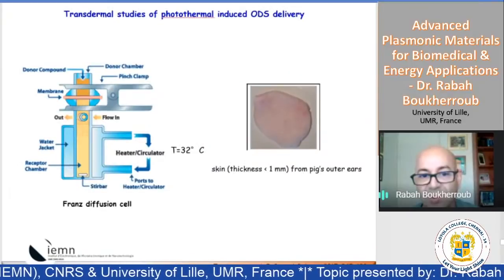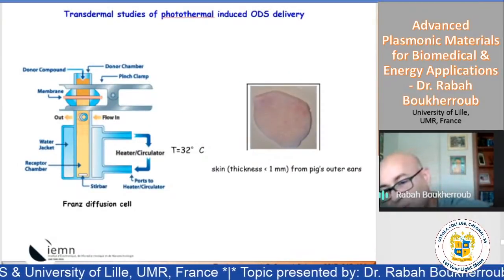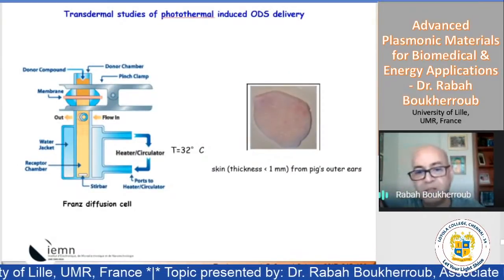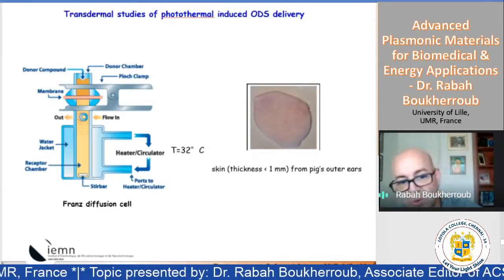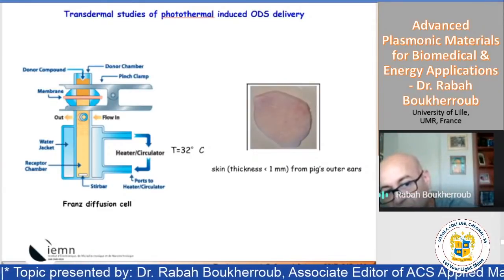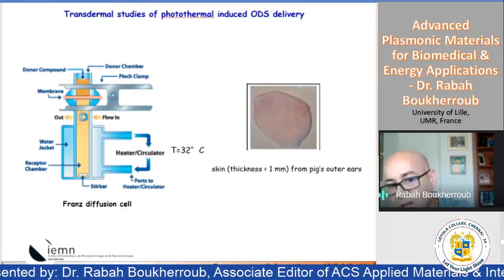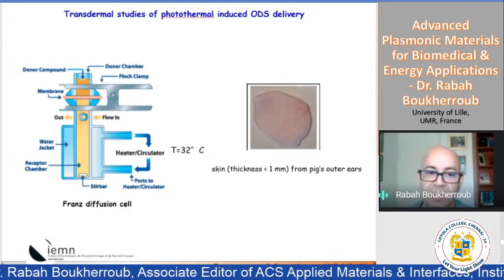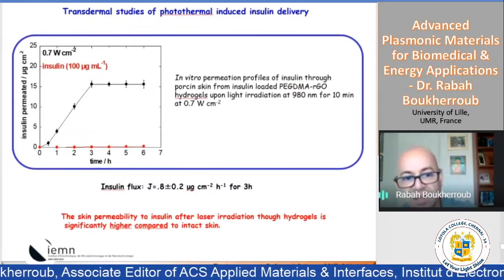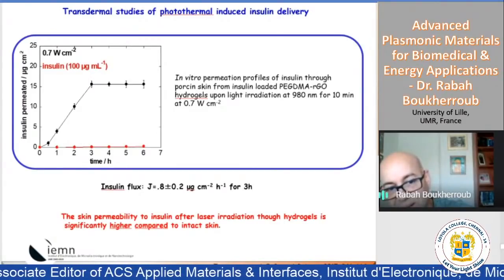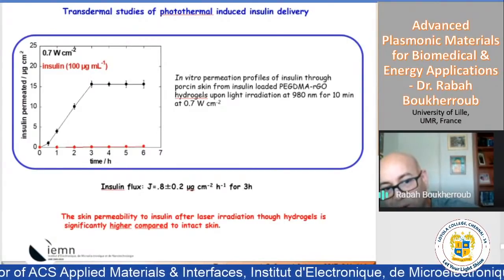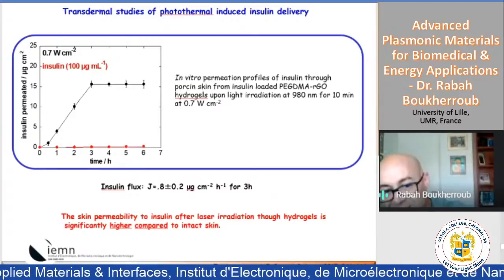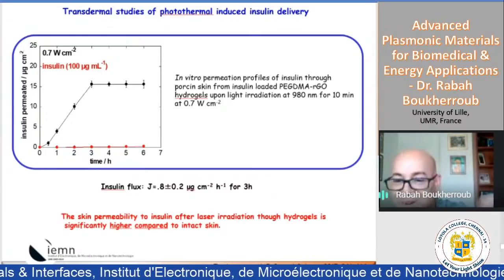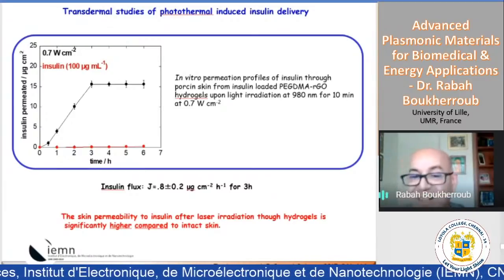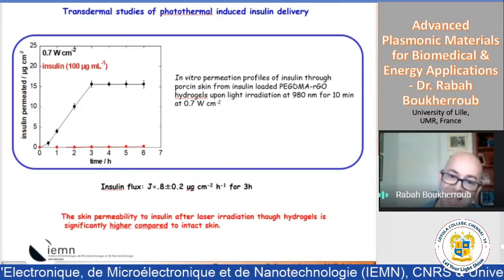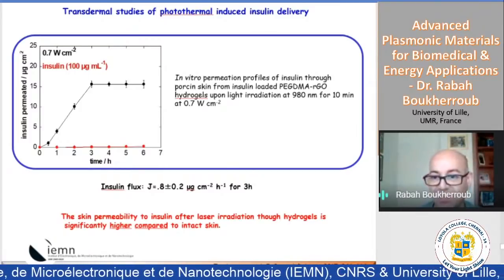So the way you do it, you take this pig, you apply the patch on top, and you irradiate, and you look if there's anything that can diffuse through. Then you get it here in the small vial, and you can analyze whether the insulin can. And we see very nice pharmacokinetics. You have slow insulin diffusing through the skin, but it's very slow. You cannot really make use of it for real application. But this is science, of course, and it takes time to optimize that.